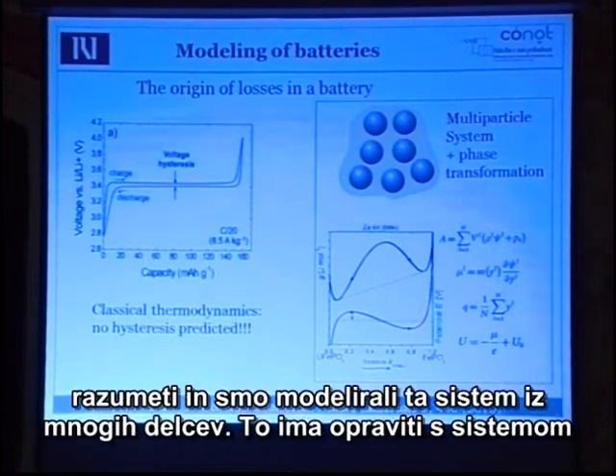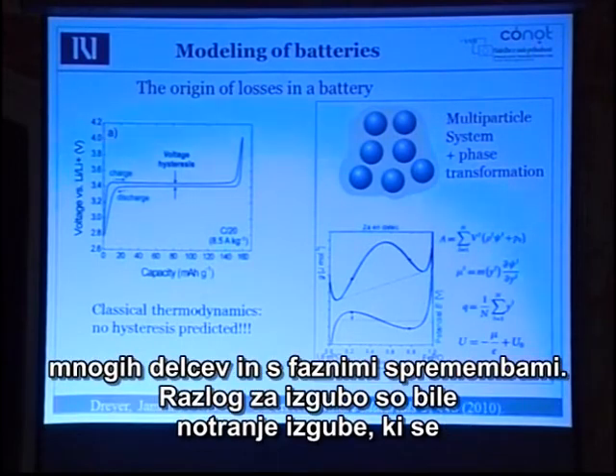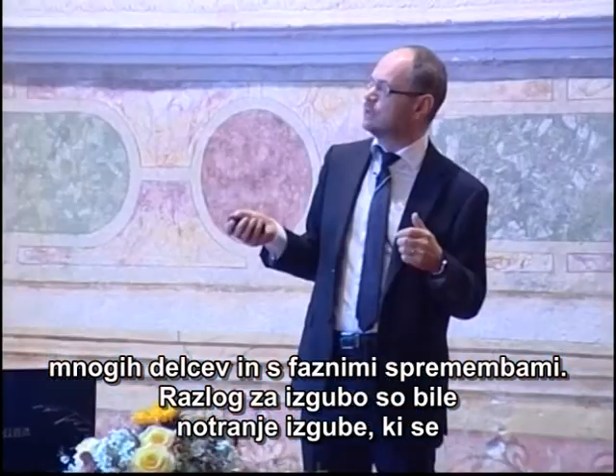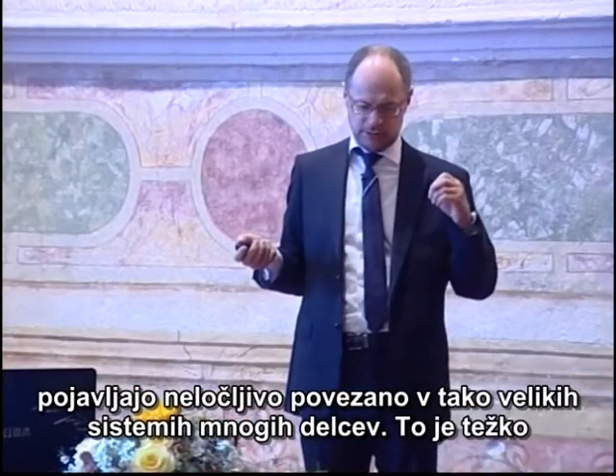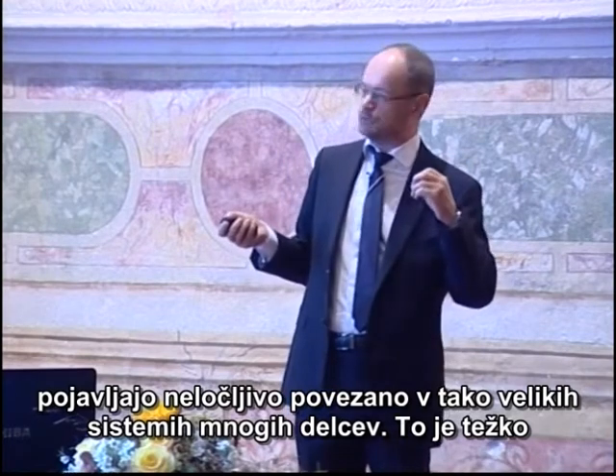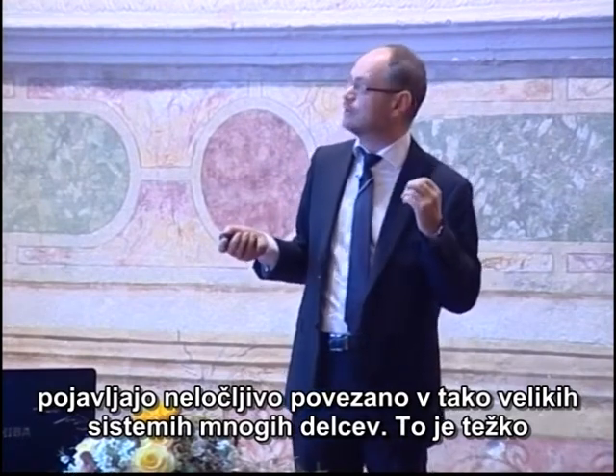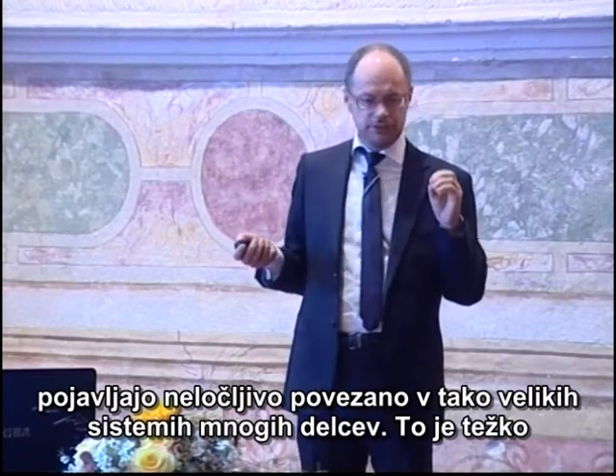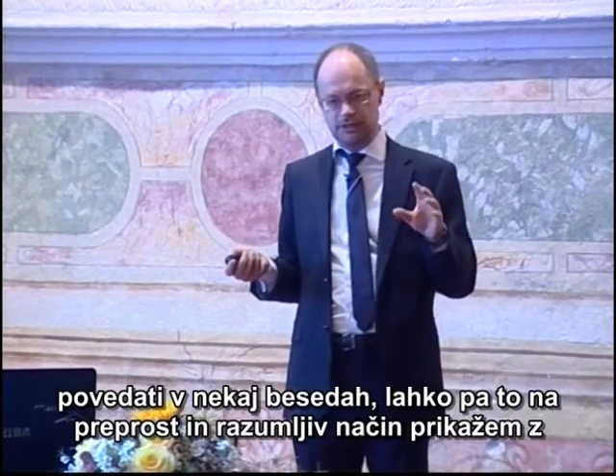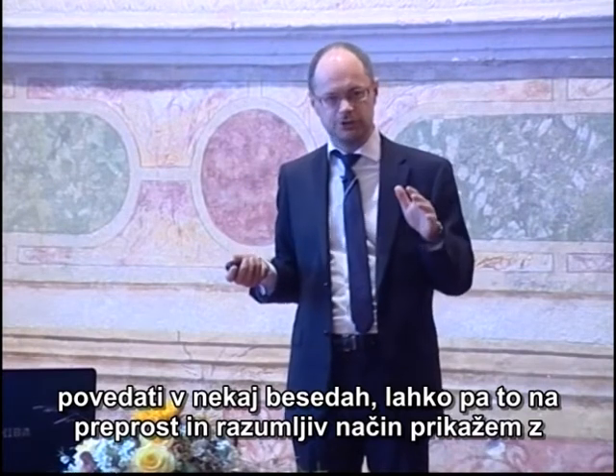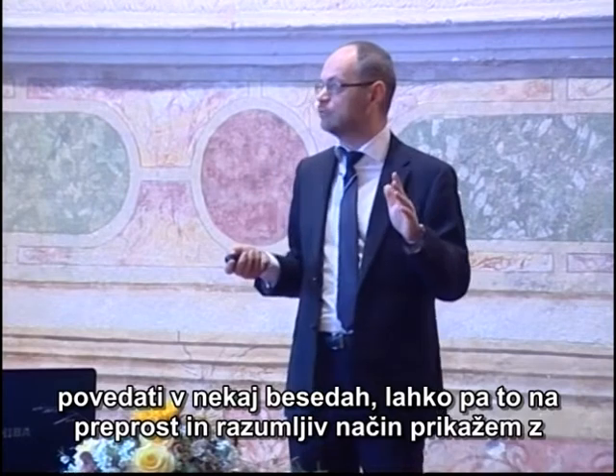So we tried to understand this, and we regarded, of course, this multi-particle system. It has to do with the multi-particle system. It has to do with the phase transformation that occurs inside these particles. We modeled this using appropriate equations, and we found that this was really the reason. The reason was the internal losses which occur inherently in such a multi-particle system. This is very difficult to explain in a couple of words, but it can be shown by analogy in a simple way so that everyone can understand.